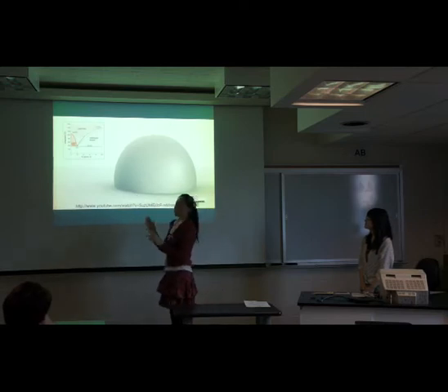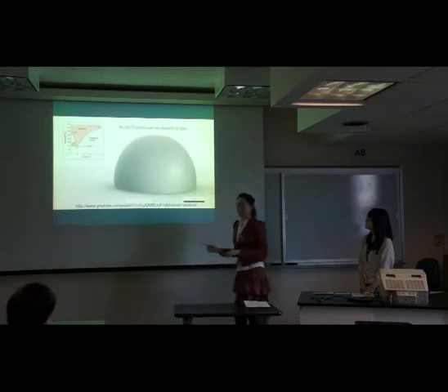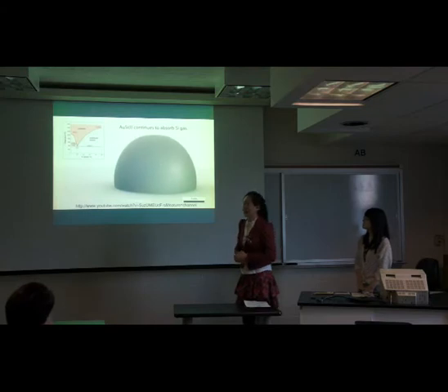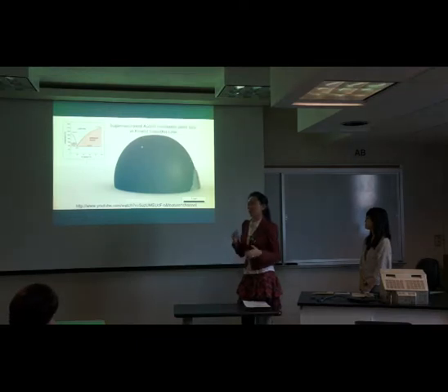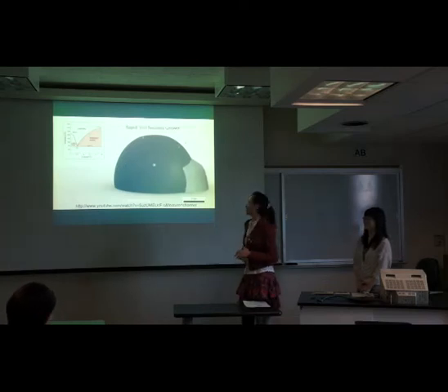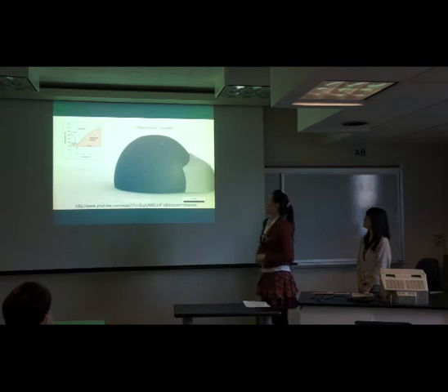We can see from this phase diagram that the gold particle melts into a gold-silicon liquid alloy. If we keep adding silicon gas into this system, the silicon will become supersaturated and nucleate, and then form the growth of one-dimensional nanowires. So we can see here the silicon nanowire growth.